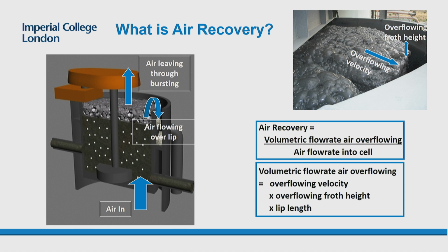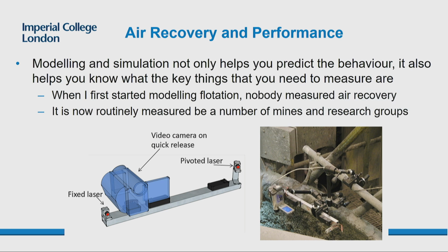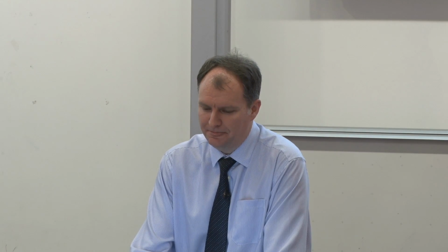We can measure, using a camera, the velocity of the froth overflowing. We can have a laser height measurement to measure the depth of the froth flowing over the side of the cell. And we know the length of the lip. So multiply those things together and you get the volumetric flow rate over, and we know how much is going in, or at least if the industrial equipment is particularly well calibrated, you know how much is going in.